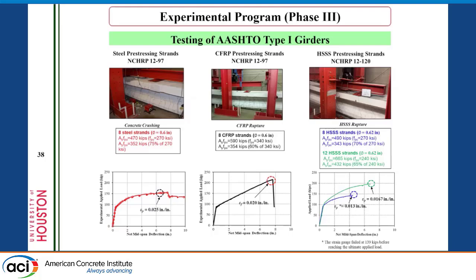At the end, we tried to compare the CFRP, the stainless steel, and the carbon steel. You can see here the red one is the conventional carbon steel, the black one is CFRP, and the blue one is the stainless steel. If we compare the blue one and the red one, they are the same except the blue has lower deflection, which is because of the strand rupture.